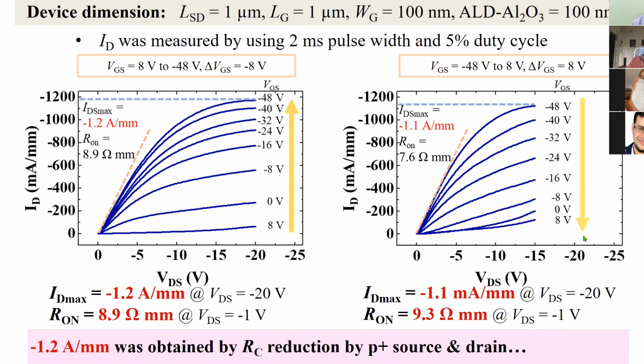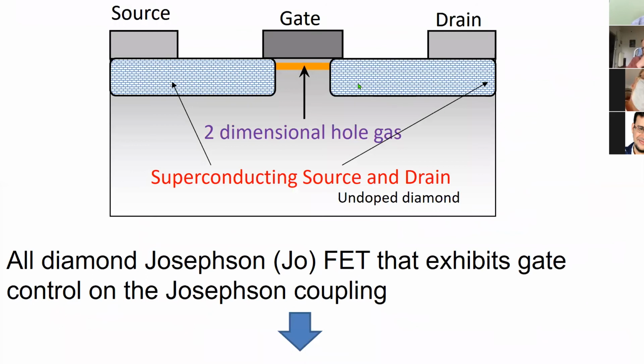This is the current density we achieved, one of the best in diamond. It's not as good as gallium nitride, but better than silicon carbide, so this is one of the good values among wide band gap materials. Anyway, what we want to show here is that this two-dimensional hole gas is our only chance for the current we obtained.